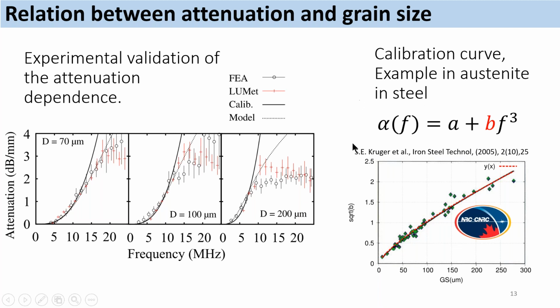So I'd like to point out this very first calibration, which was done by the CNRC in about 2005, which was a breakthrough in metallurgy because it allowed the measurement of the austenite grain size in real time. As we know, austenite is a phase which is stable only at high temperature, and so it's often a challenge for metallurgists to control this austenitization treatment because they don't know the grain size that they have in their furnaces. Therefore, using this machine, we can access in real time the grain size in austenite for various conditions.